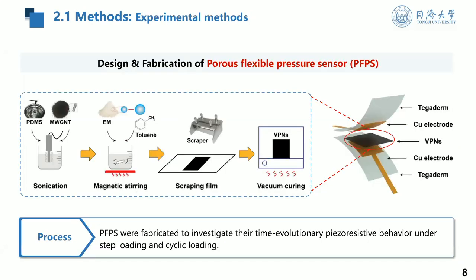First, we designed and fabricated a porous flexible pressure sensor. Here we use PDMS as the matrix, and we use multi-walled carbon nanotubes as the conductive fillers. And then we use expandable microspheres to control the porosity in the nanocomposites.